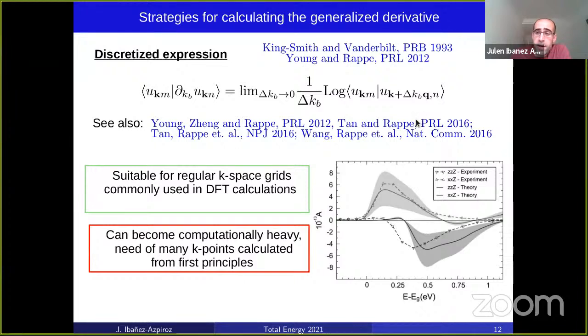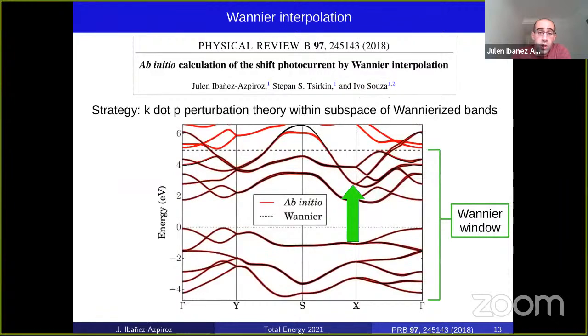Here on the right, we show barium titanate, where the theory matches very well the experimental values, and even the trends are well reproduced. But on the other hand, this scheme can become computationally heavy, as it needs many k-points for first principles. Each wave function needs to be calculated by ab initio methods at each k-point. So if we want to study systems where we need a lot of k-points, like 2D systems or even Weyl semimetals, then this would become computationally heavy. So that's why we have considered an alternative strategy, which is to consider Wannier interpolation.